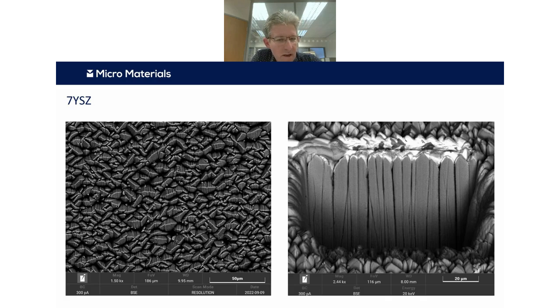It's a columnar material, and at the top you can see these columns, and they create a certain roughness. There's a FIB cut on the right, and you can see the columnar structure, the porosity, and the roughness from the columns. There's also a little bit of platinum on the top that's just been used as part of the FIBbing process.